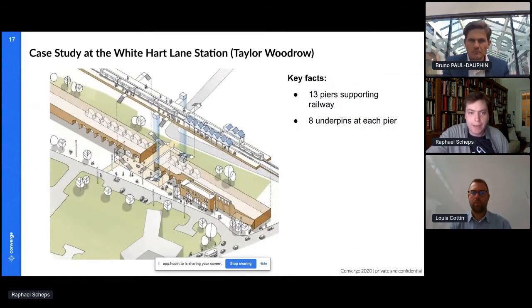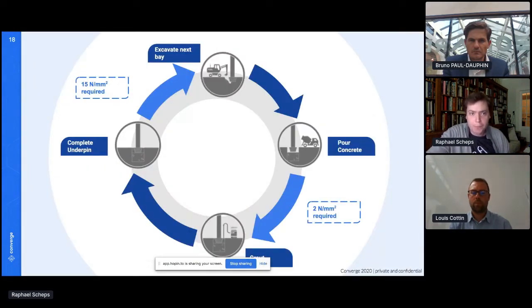So to explain the use case, you had about 13 archways, which you can see on the screen here. So 13 piers supporting the railway, and a new structure was going to be built on top. Underneath each pier, you had about 8 underpins that needed to be built in a sequence. And Concrete DNA helped optimize that sequence, which was strength dependent. So every time a new bay had to be built, it had to be excavated, the concrete had to be poured, and then the site operatives had to wait until that concrete reached a strength of 2 megapascals before they were able to grout. And that was milestone number 1 that we were optimizing.